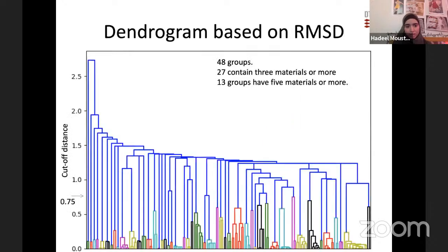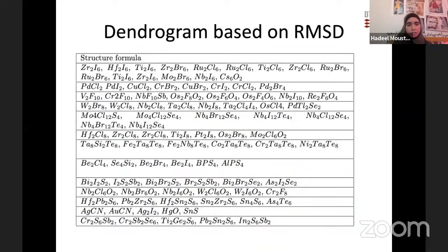We make a further analysis by looking at the single linkage clustering, which is characterized as a function of the cutoff distance, which is 0.75. And from that, we got 48 groups. 27 of them contain 3 materials or more, and 13 groups have 5 materials or more. And here we have the materials that have 5 or more.